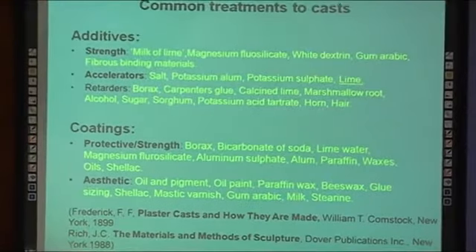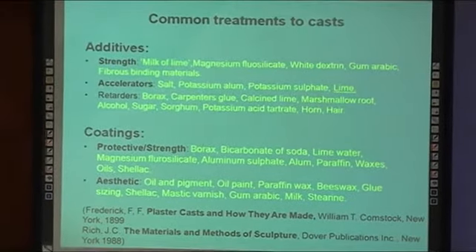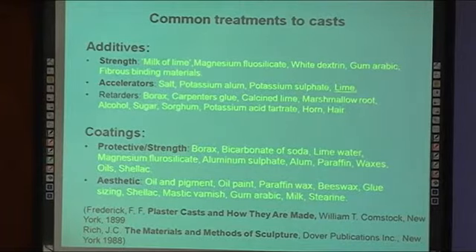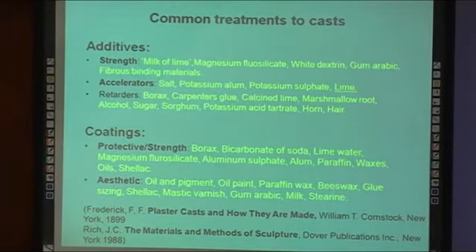The formatori were well aware of the weaknesses of plaster of Paris and often used additives within the plaster mix for strength or applied coatings to the surface for protection. They also added accelerators or retarders to the plaster mix depending on the size or amount of cast they were producing and whether they needed to hasten or slow the set of the plaster.